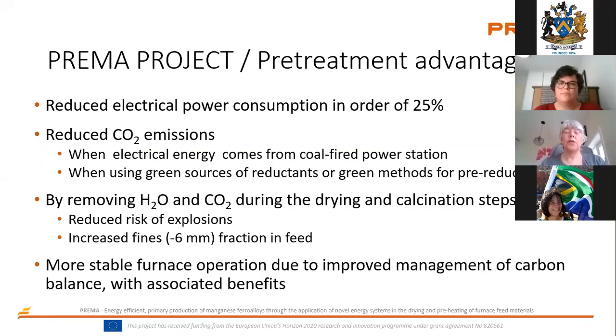You must also use green sources of reductants or green methods for pre-reduction. In addition, we will reduce the CO2 emission because we have less of the unwanted Boudouard reaction inside the furnace. Other advantages are that we will remove water and CO2 during the drying and calcination step. That will give a reduced risk of explosions, but it also increases the possibility to use fines fractions in the feed, especially in the closed furnaces, which we have a lot of in Norway. It will also give a more stable furnace operation due to the improved management of the carbon balance, especially because we have less of the Boudouard reaction. Next slide.